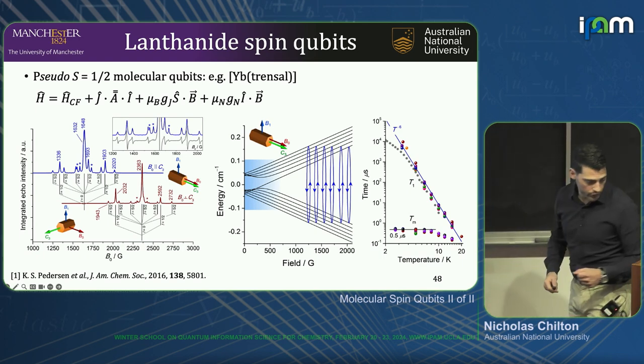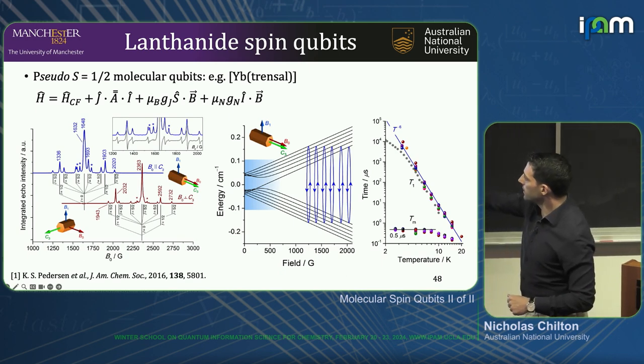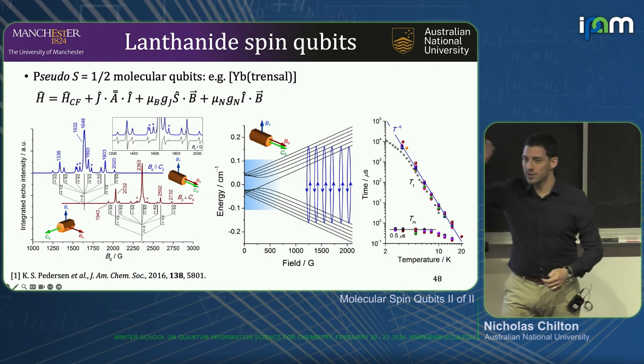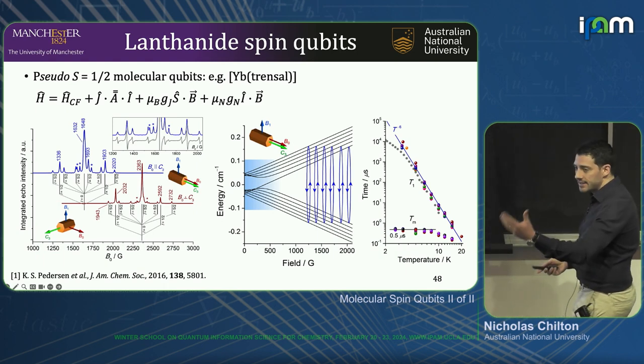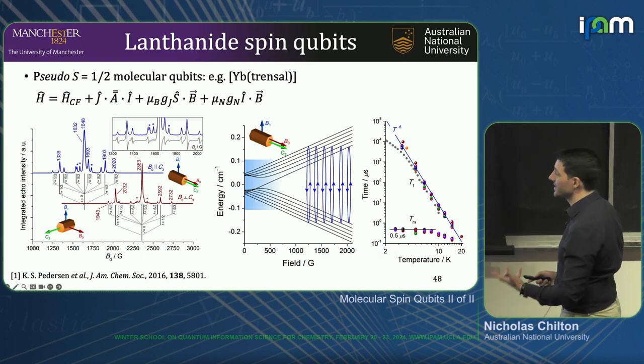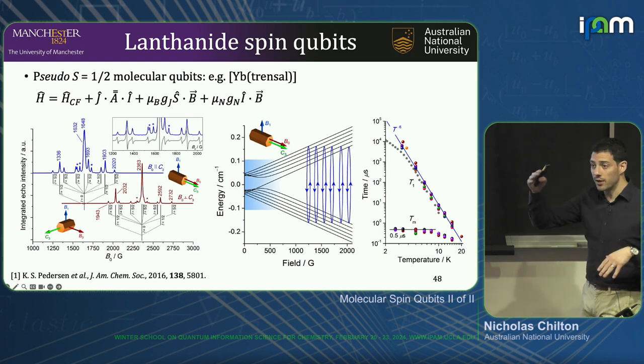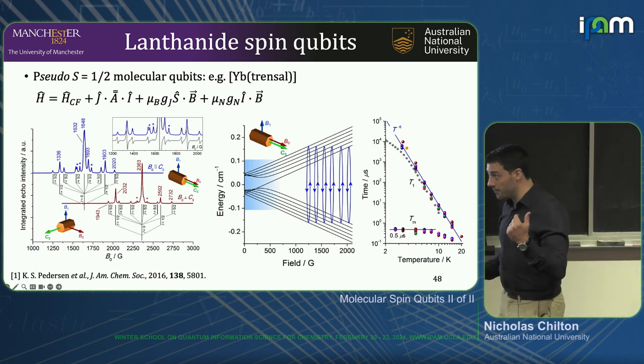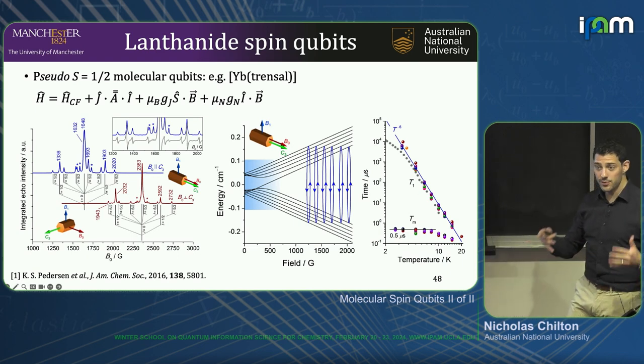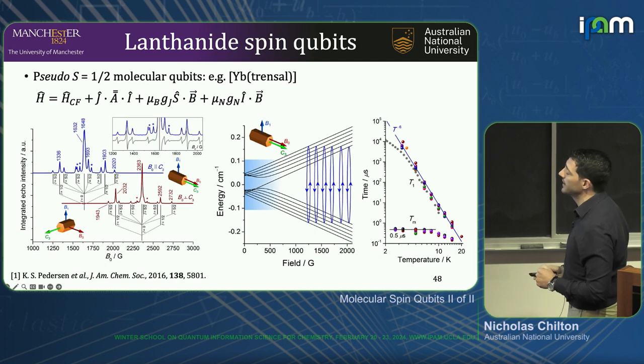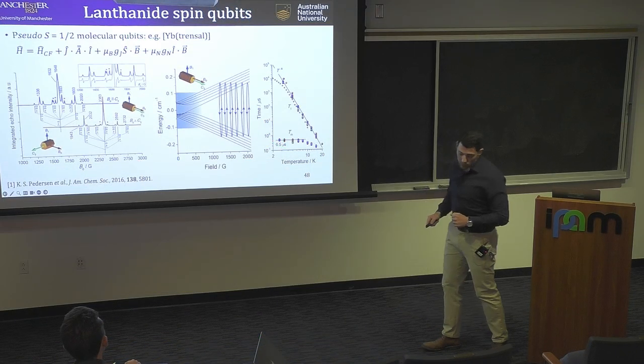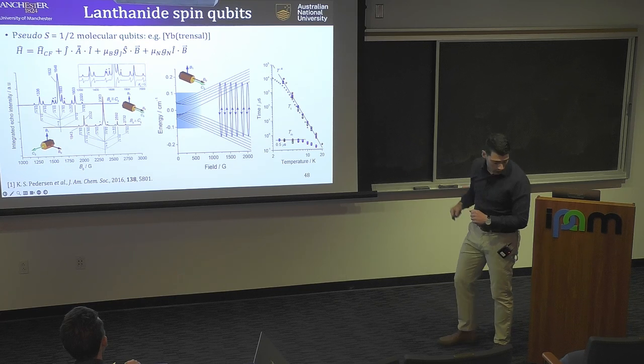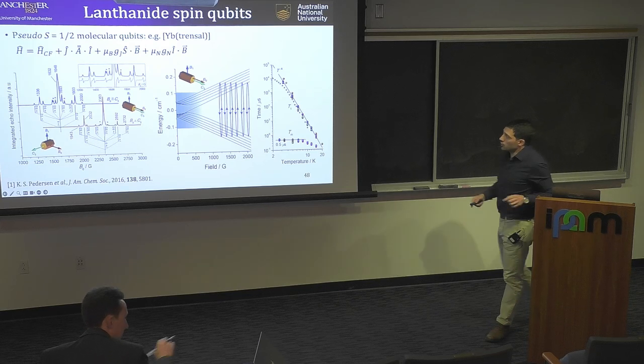This is lovely work from the Copenhagen group, measured also in Manchester for some of these experiments. The total Hamiltonian includes the crystal field, the free-ion Coulomb terms — after getting out Russell-Saunders terms and working in the total angular momentum basis — a crystal field that splits the J manifold into Kramers doublets. We add hyperfine coupling of the total angular momentum J to the nuclear spin, a magnetic field term acting on the electron spin J, and a nuclear magnetic interaction.